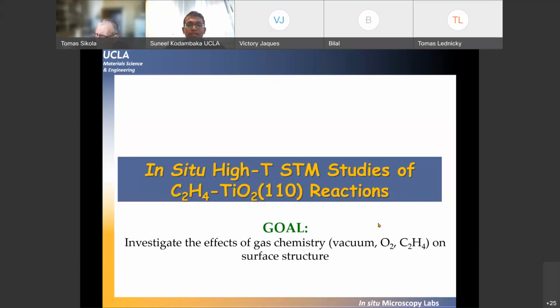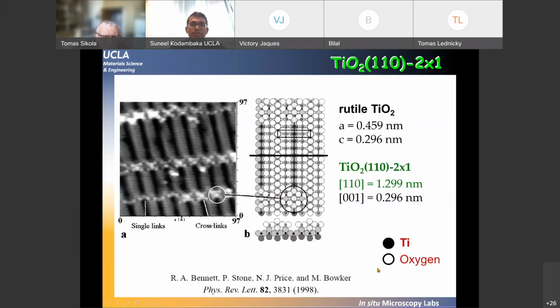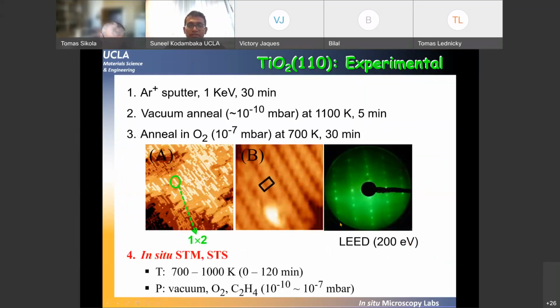the 2D layers. And here what we decided to do is to take a single crystal TiO2 and expose it to different environments, either vacuum or oxidizing environment or reducing environment. And for those of you that are familiar with TiO2, rutile TiO2, there is this so-called stripe phase, which leads to a 2x1 reconstruction. And experimentally, you would observe this both in the low energy electron diffraction patterns and also in scanning tunneling microscopy images. These are these stripes that appear.